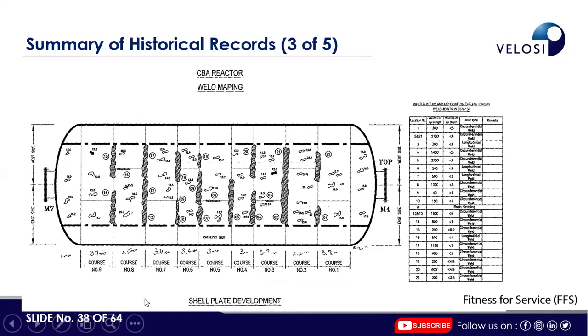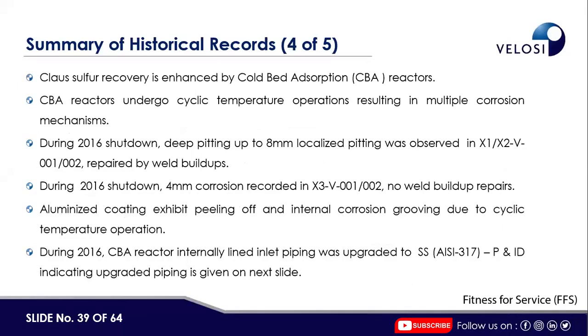Okay. Now, summary of the historical records. Claus sulfur recovery is enhanced by the cold bed absorption reactor. The CBA reactor undergoes cyclic temperature operations resulting in multiple corrosion mechanisms. During the 2016 shutdown, deep pitting up to 8 mm and localized pitting were observed in these vessels, and those were repaired by weld buildups. During the 2016 shutdown, 4 mm corrosion was recorded in V001, V002; no weld buildup repairs were done. Aluminized coating exhibits peeling off and internal corrosion grooving due to cyclic temperature operation.